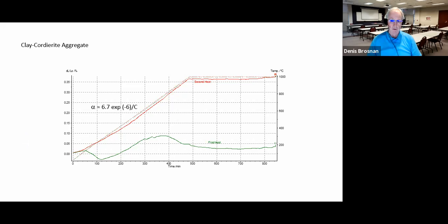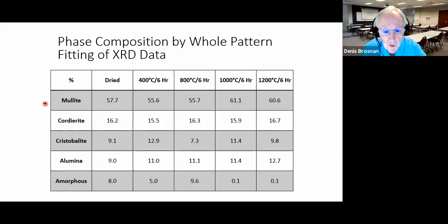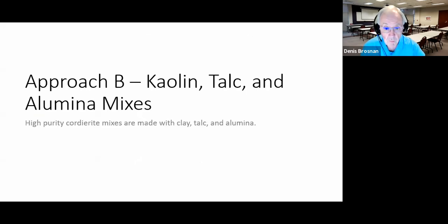Well, that's pretty darn high. The reason it's high is that the semi-cordierites that were made in this example contain a lot of mullite. So the thermal expansion coefficient of the article that's been made is more similar to mullite than to cordierite. It's pretty high, 6 to 7. So they don't contain very much cordierite, but they contain a bit of cordierite. So there we go. That's one way to make it.